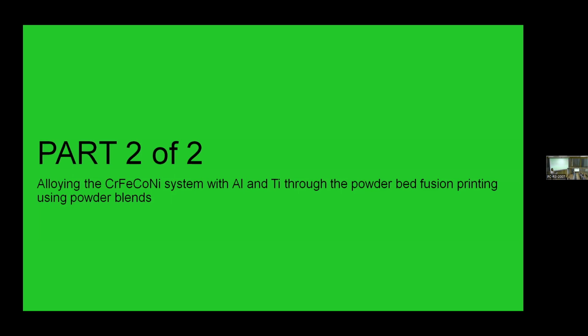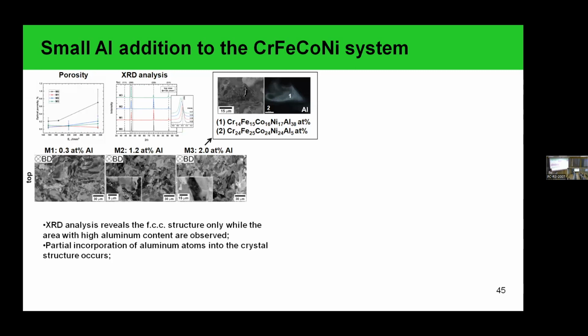Coming to part 2, alloying our system with aluminum and titanium, we start from a small aluminum addition to our 4-component system. We prepared a set of parameters where we applied different laser power and laser speed. An interesting observation is that even the small aluminum addition leads to lower porosity for all considered regimes which we used for the printing. XRD analysis demonstrated the formation of the FCC phase only, but we observed a shifting of the peaks of our material, which can be interpreted as incorporation of aluminum atoms into the crystal structure.